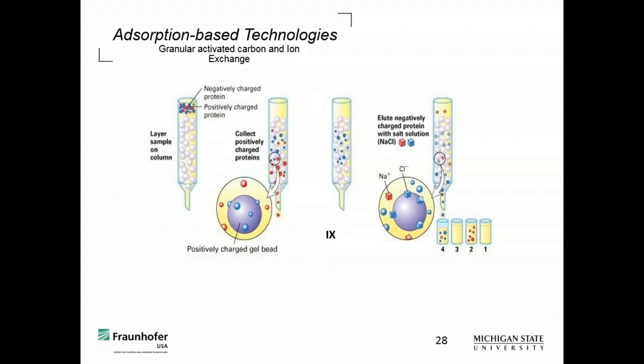Ion exchange gives you an added advantage. Remember I said hydrophobic tail, hydrophilic head. The activated carbon is really geared towards the hydrophobic tail. But with ion exchange, you can fabricate resins that have dual sites. You can have the cross linker that can adsorb the hydrophobic portion, but then you can also have a cation exchange or an anion exchange resin that can electrostatically attract that acid group. So you sort of double your capacity, and you intrinsically eliminate this issue of one chain length being more hydrophobic than the other, because you can get it by electrostatic attraction. Those are some of the advantages of using ion exchange, this dual capability.